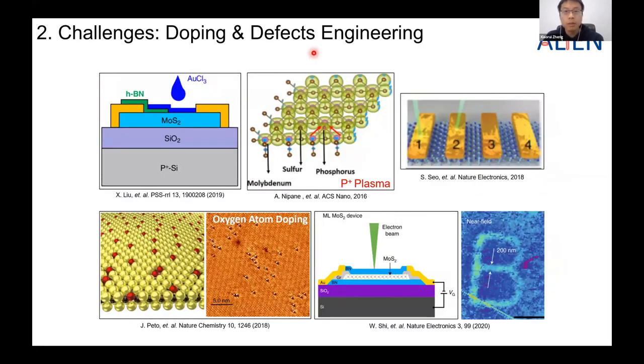In terms of the bipolar conduction, people use doping or defect engineering to achieve it, like chemical doping of MoS2 to achieve P-type doping, or plasma doping techniques, and recently laser-induced doping, and oxygen atom doping. And this year, people demonstrated using an electron beam to dope multilayer MoS2 devices to P-type. So these are all very interesting techniques.